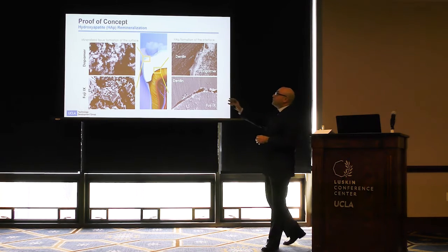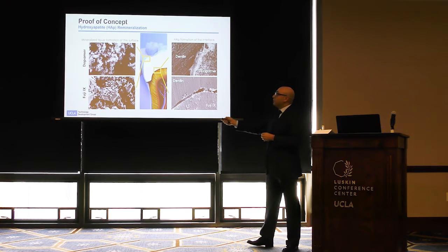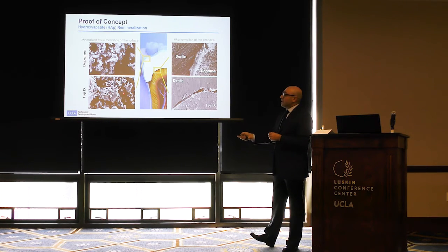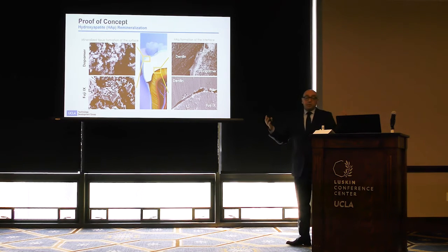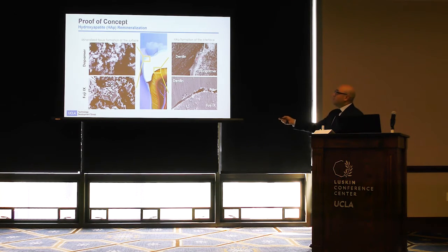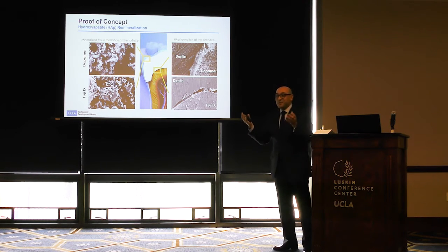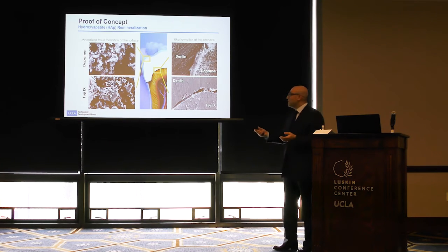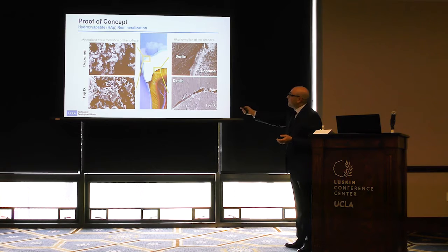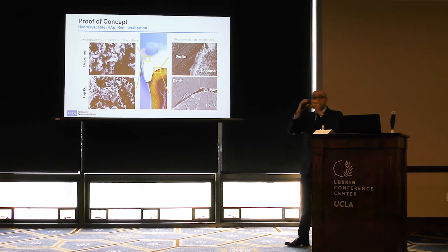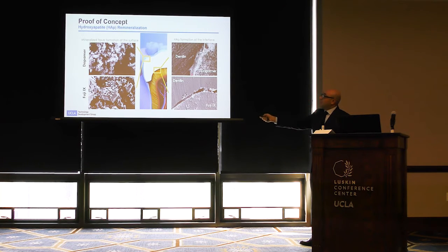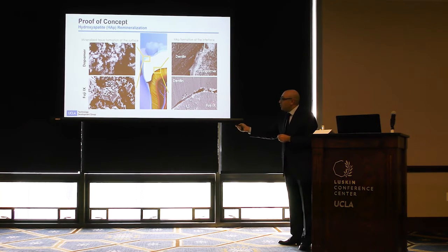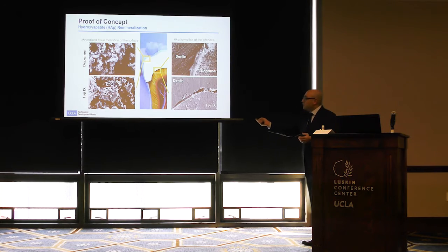After that, we utilized our Dopamer filling material for filling enamel and dentin, and again we compared it with Fuji 9, the commercially available product. What we showed is a significant amount of hydroxyapatite formation, mineralization at the surface of enamel whenever we have our Dopamer filling material. At the interface of dentin, you can clearly appreciate that we have a rich calcium phosphate layer, the mineralization layer between the dentin and Dopamer. When you compare this with Fuji 9, our commercially available product, you see a gap.